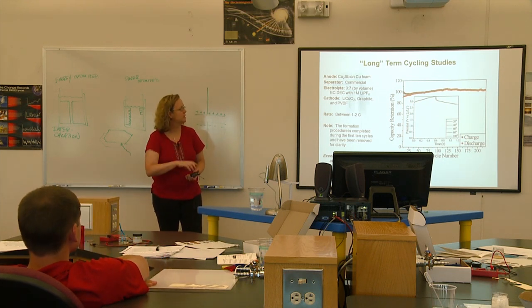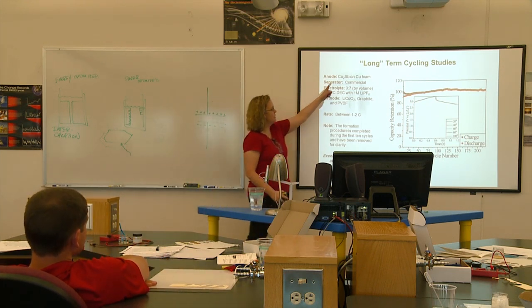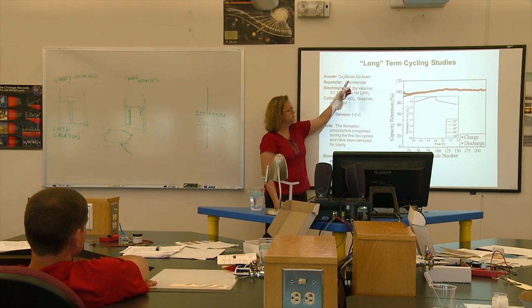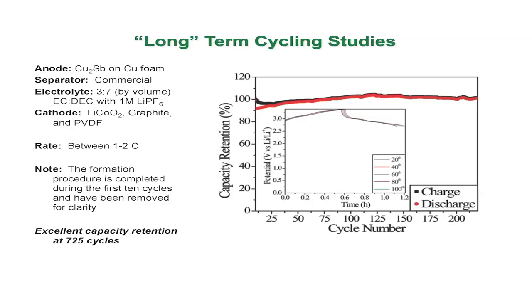So what we did here is it's our anode, copper antimonide on our copper foam, but we used a normal separator. This is the flammable liquid solvent that's in your cell phone. We use the exact same one. This is the salt, LiPF6, that if it sees water, it makes HF acid, and that's what etches bones, so that's the bad part, but we used it for this test. Cathode is the commercially available cathode. We packaged it in the size and shape you would use for your phone, and we cycled it.